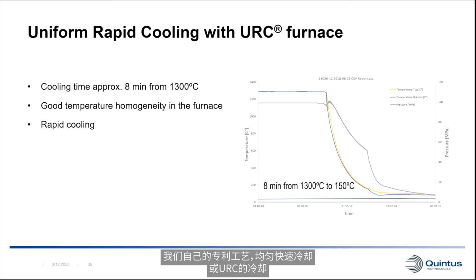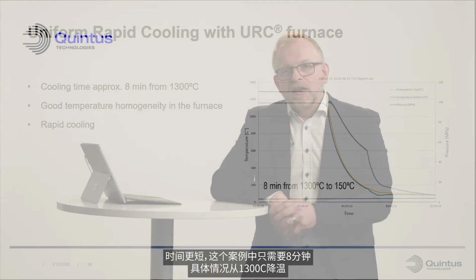Our own patented process, which is uniform rapid cooling, or URC, is a much shorter cooling time, and it takes only 8 minutes in this particular case from 1300 C. And good temperature homogeneity is seen throughout the furnace, because we're using either ejectors or a fan to drive the flow of the gas. And this gives us really rapid cooling, which is very, very useful for additive manufactured parts.